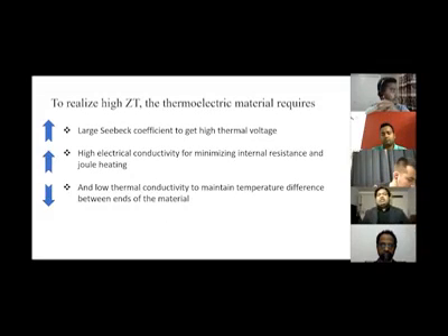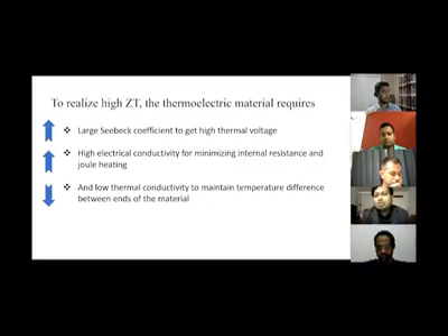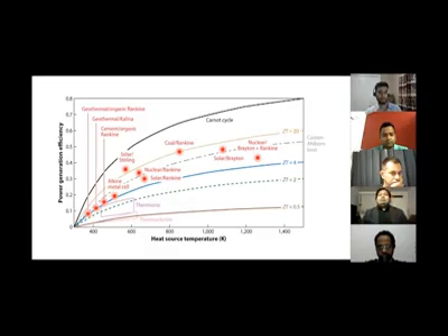So here we already said that to have a good thermoelectric material, we need a large Seebeck coefficient so that we can get a high thermal voltage. It should have very good electrical conductivity to minimize the internal resistance. At the same time, it should have very low thermal conductivity so we can maintain the temperature difference between the two ends. This is not very easy because they are interlinked. Here we can see a relation between the ZT value and the efficiency. So if you have a material whose ZT value is 0.2 or 0.5, and if you're